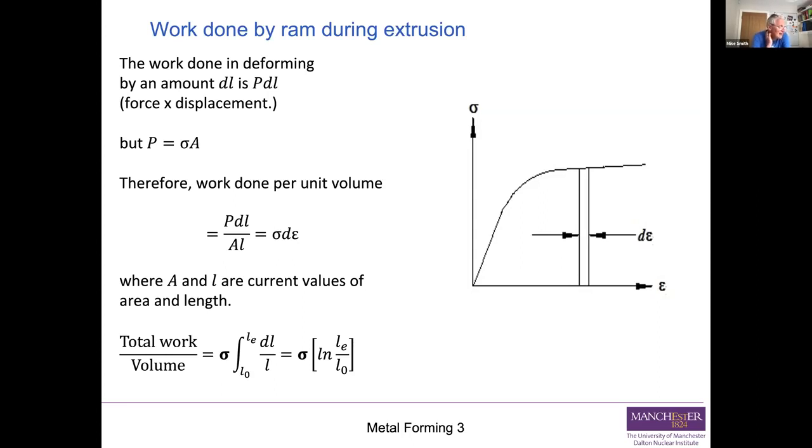between L0 and LE, and you've got a dL over L there, so you can see that you're integrating the equation that's halfway up that slide, and that works out as sigma log e of LE over L0. So we now have a relationship between the total work done and the stress. So what can we do with that?